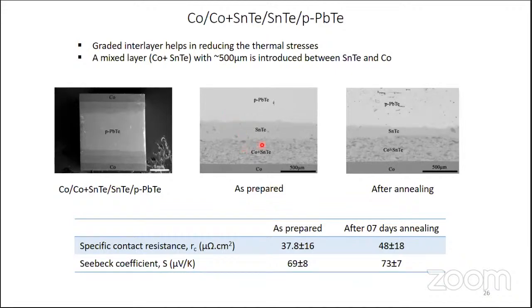Here you may ask why so many layers. It is not only the diffusion, it is not only thermochemical stability, as I was talking about thermophysical stability. It means a gradual variation in the stress should be there. Otherwise, a crack will form between the layers. Interfaces will crack. So when we directly put tin telluride, it works, but mechanical damage occurs. So that is why we put a 50-50 layer. Here you can see that after 7 days, as prepared and annealed, absolutely the same Seebeck coefficient.